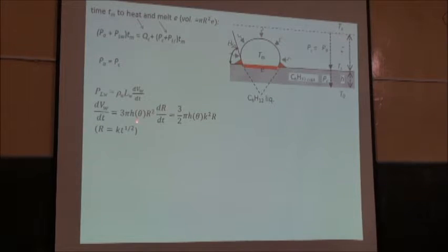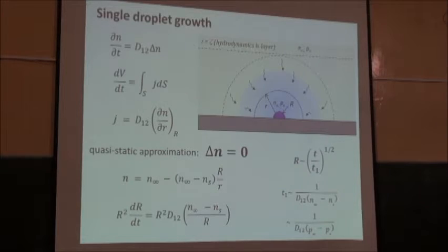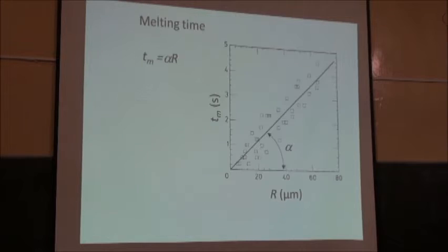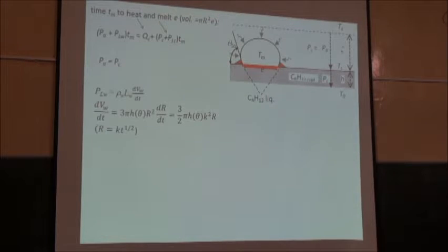That's a geometrical factor, and that's the volume increase. And so you get something which is proportional to k squared r, proportional to r, according to this growth law. R is proportional to time, r is equal to k t to the one half, and so you get this equation simply, that is dV over dt is proportional to the radius from this growth.